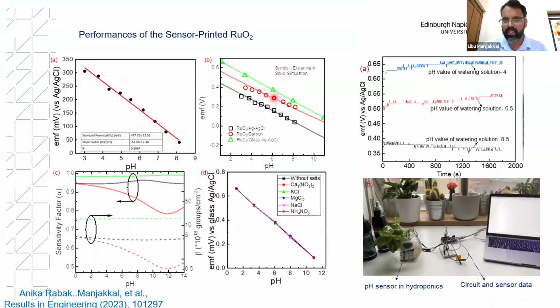And also its simulation, we did in collaboration with Glasgow University. We measured the sensitivity factor of the sensor, and you can see here that there are different salts. For example, in a soil, there are different types of salts, like sodium chloride, magnesium chloride, or potassium chloride. We monitored the presence of salt, and to analyze the selectivity of the sensor, we got the best performance for the sensor, and also the pH value of the watering solution with stable performance. There is a small drift here, but it is negligible because of the large value here.